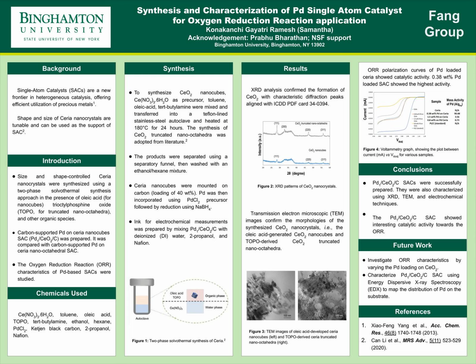Moving on to the results. X-ray diffraction, or XRD, reveals that CeO2 nanocrystals were formed since the characteristic diffraction peaks observed in the XRD pattern matched with those in the standard ICDD card. We study the morphology of the crystals using transmission electron microscopy, or TEM. As you can see on the left side, there are nanocubes of CeO2 which were synthesized using oleic acid, and on the right side you can see truncated nanooctahedra which were synthesized using TOPO.